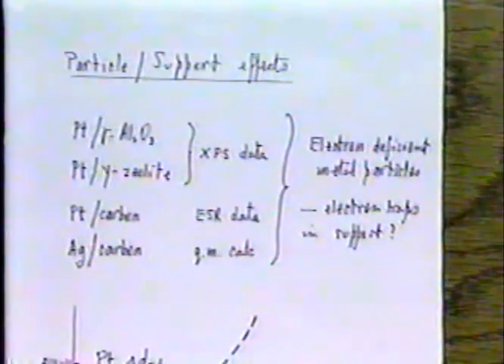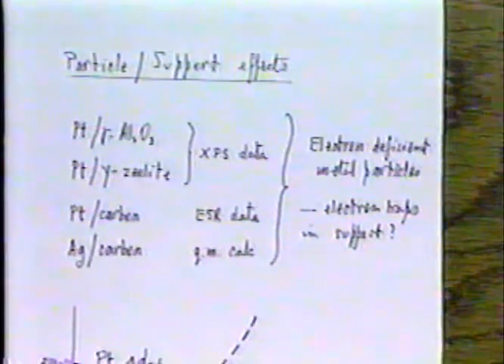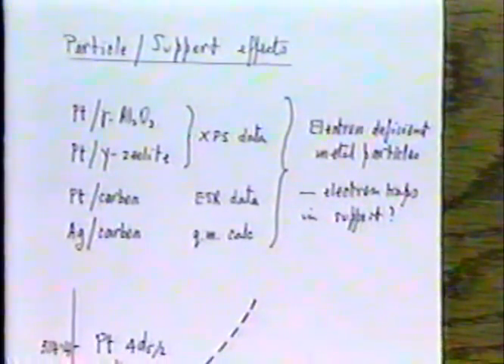What this sheet does, first of all at the top, is to summarize some of the quite large body of data, and gives you some idea of the sorts of things that have been observed. There is really quite a lot of data now which shows that small platinum particles sitting on the surface of gamma alumina, or on the internal surface of, say, Y zeolite, small platinum particles, which are typically 10 to 20 angstroms in size, behave as though they're electron deficient. They behave as though the interaction between the platinum and the support has made the metal more electronegative, makes it more difficult to extract an electron.